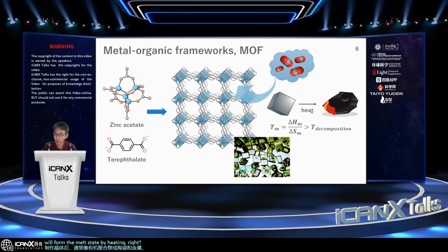We can discuss the melting point. But this kind of compound usually changes irreversibly into something different, such as carbon materials or metal oxide, by heating without forming a melting state. So this kind of compound didn't have any stable melt state by heating, which prohibits wide utilization of the materials by use of the phase change. The reason is very simply described like this: the melting temperature is the ratio between the delta enthalpy and delta entropy between the crystal state and melt state. And usually this melting temperature is above the temperature of decomposition by heating. That's why we couldn't find the melting structure of this type of metal organic framework.